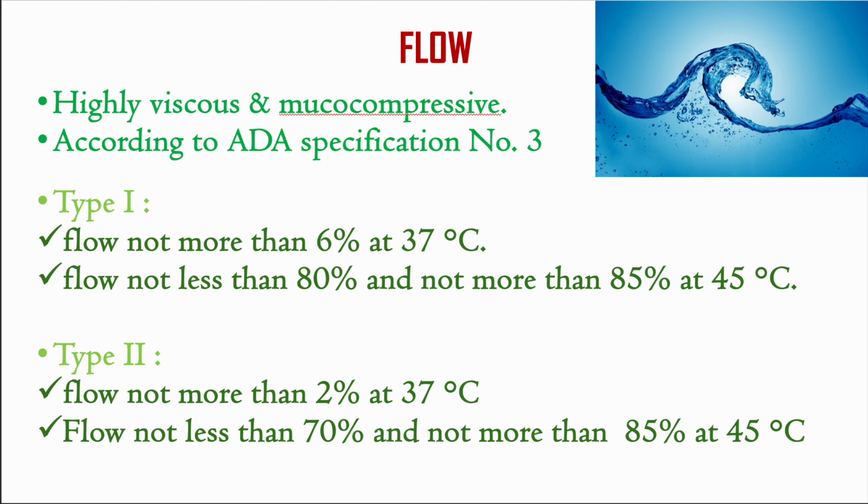Now coming to the flow property. Highly viscous and mucocompressive is our impression compound. According to ADA specification number 3, type 1 has flow not more than 6% at 37 degrees Celsius, and flow not less than 80% and not more than 85% at 45 degrees Celsius. For type 2, the flow is not more than 2% at 37 degrees Celsius, and the flow is not less than 70% and not more than 85% at 45 degrees Celsius.